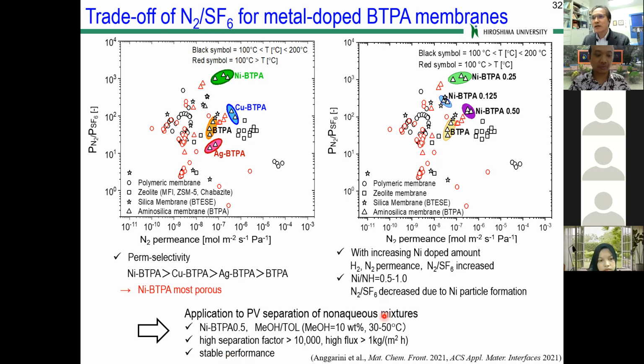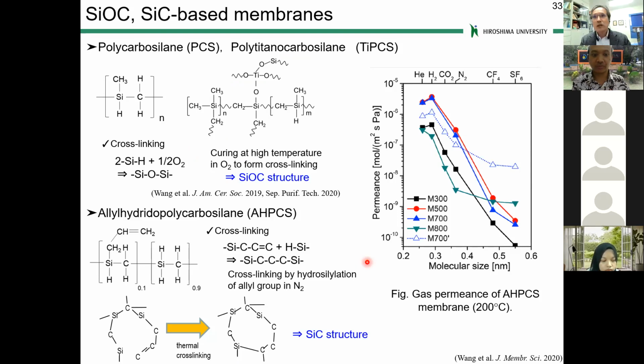Now, we also work on silicon oxycarbide or silicon carbide type membranes prepared from polycarbosilane, PCS, or polytitanocarbosilane, TiPCS. And also we work on allylhydridopolycarbosilane, AHPCS. These precursors are thermally cross-linked to form the SiC network. So we expect this SiC network to be very stable at high temperature and also in steam atmospheres. Here we have permeances plotted as a function of the molecular size of these gases. You can see hydrogen shows very high permeance, higher than 10⁻⁶, with a very sharp selectivity of hydrogen